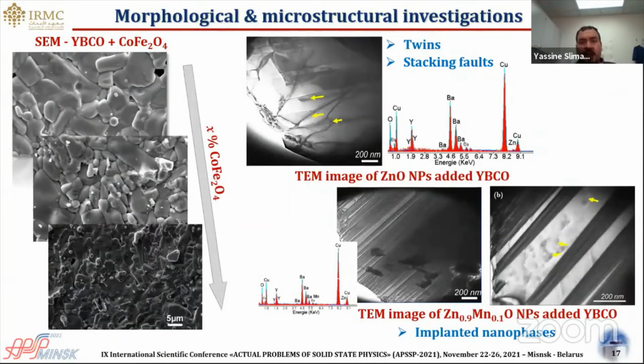For the case of adding magnetic nanostructural materials, we found, for example, that the grain size reduces greatly with increasing content of magnetic nanoparticles. So it is evident that the type and nature of the incorporated nanostructural materials affect the morphological properties in different ways.